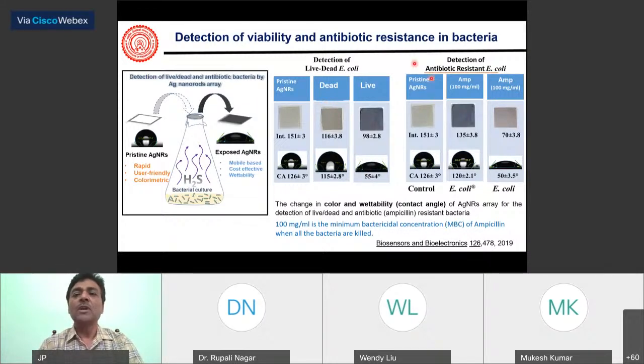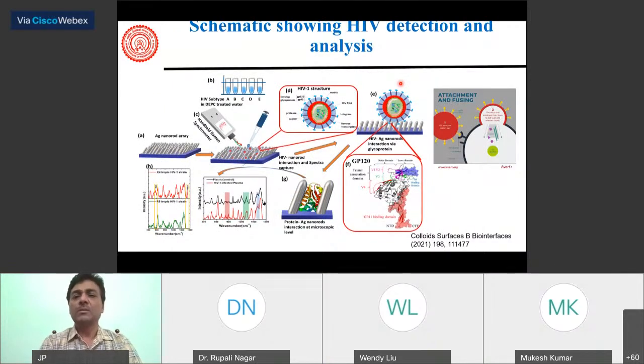We also found this on E. coli, and this result I'm showing is for E. coli, but we have done it on 10 different kinds of bacteria, and for gram-negative bacteria we found this is quite effective. We found that it works even for antibiotic resistant bacteria, and we were able to differentiate between antibiotic resistant bacteria and normal bacteria. Since this work was already shown yesterday, I'm not going into detail here.